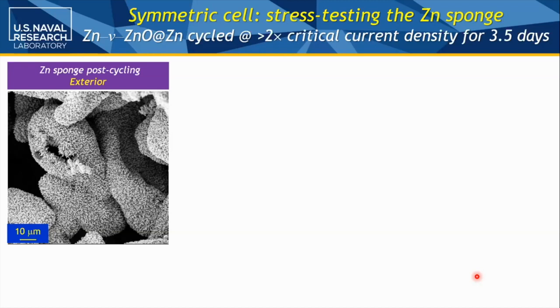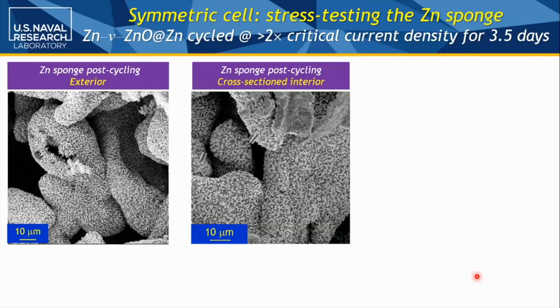In the modern day, yes. So we put a zinc versus a slightly zinc oxide coated sponge and just cycled it twice the current critical current density in an alkaline electrolyte, and that went on for 3.5 days. Took it out, rinsed it off, put it in the scanning electron microscope, and you can see the exterior has this nice sort of texture everywhere. You cross-section, you see the same texture.